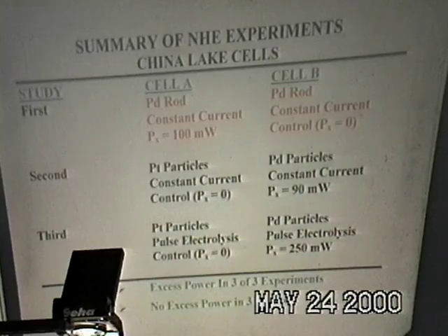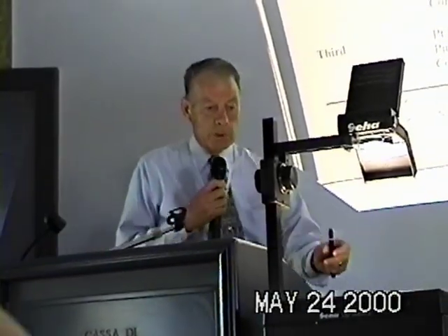And then I tried platinum particles and palladium particles, excess heat with the palladium particles, but none with the platinum particles. And this was a continuation of the same experiment where I went to a different type of electrolysis, pulse instead of constant current, with Dr. Tripodi's help. And the excess heat got larger, as you see, and still no excess heat in the platinum material. So this just summarizes very briefly the China Lake calorimetry. At all times I had 5 calorimeters running, 2 of my own from China Lake and 3 of the Fleischmann Pons type, and that will be the focus of my talk today, the Fleischmann Pons calorimetry.